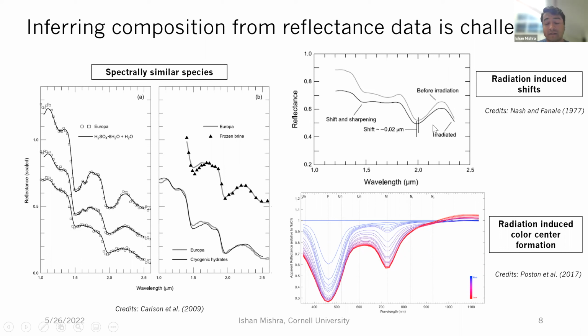Then there's another effect that we see, which is shifting of spectral bands due to irradiation. So your water ice shell around your hydrated salts are getting distorted because of irradiation, and that changes the fundamental energy levels and shifts the band. And so this has been seen in the lab. This is also seen in the Europa data. So it's something to be taken into account when we are trying to detect species and get at their abundances. And something that I mentioned, which is formation of new spectral features.